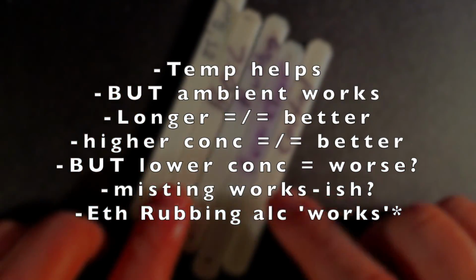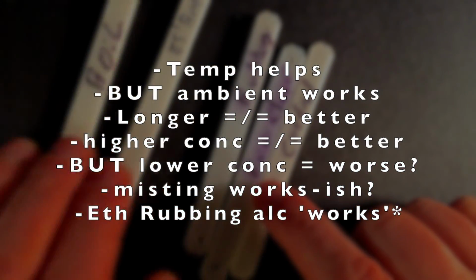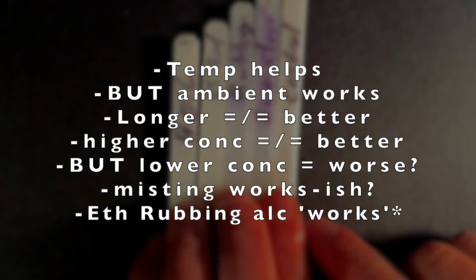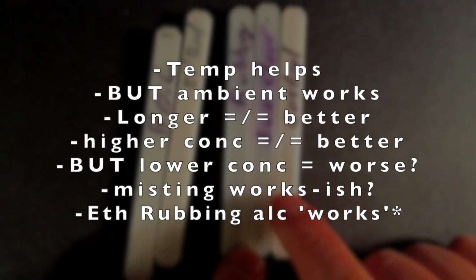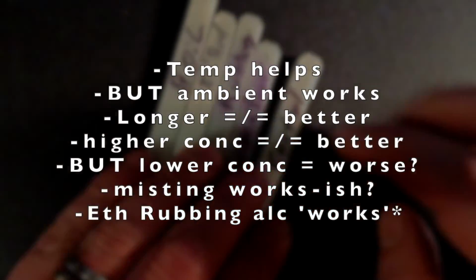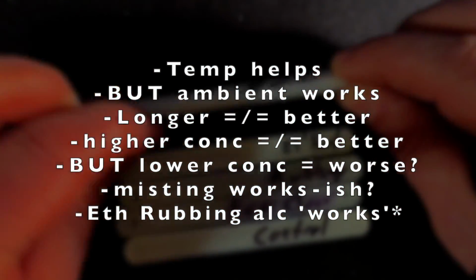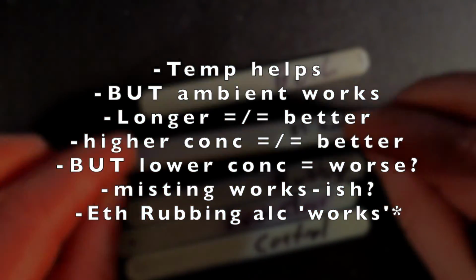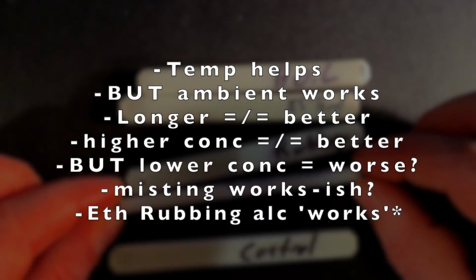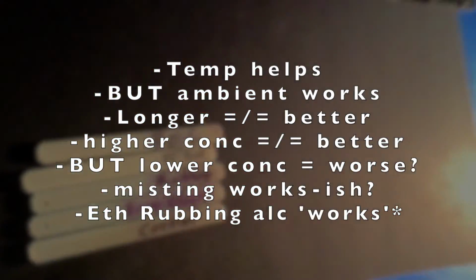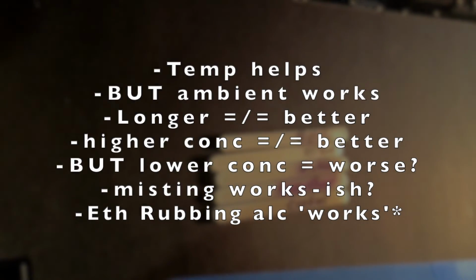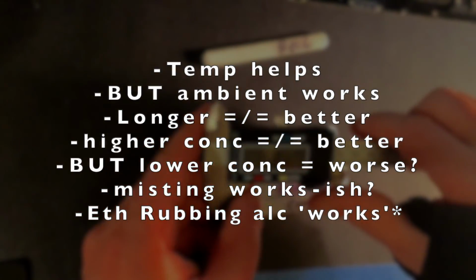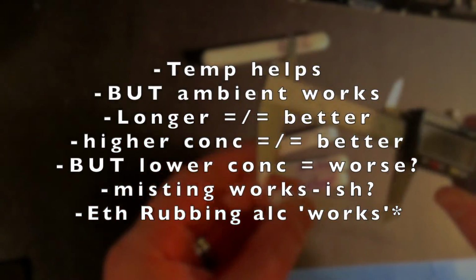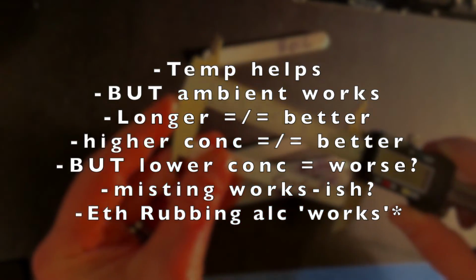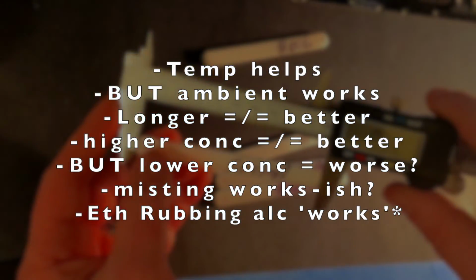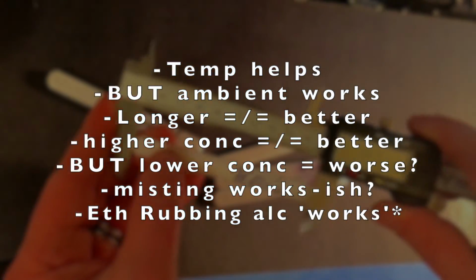So, anecdotal observations from me from this small uncontrolled data set here. The higher temperature does help, as in heating up the alcohol to like 40, 45 degrees, not up to dangerous combustion temperatures or anything like that. But ambient does work, just not as well. Also, leaving it in longer doesn't necessarily make it better. You saw with the 7.5 versus the 30 minutes in the alcohol, there wasn't really that much of a difference. That tells me that the crystallization happens very quickly, so probably within the first 5-10 minutes, it's about the best you're going to get.